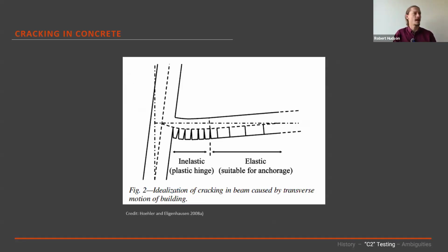The other thing we care about with regards to cracking is the size. The larger it is, the more adverse impact it's going to have on our post-installed anchor connections. Now, there are two numbers to be aware of, and I suspect you're all going to be sick of me saying these numbers by the end of the webinar: a 0.5 mm crack width and a 0.8 mm crack width. The 0.5 mm crack width is very roughly intended to represent service conditions and moderate seismic events, and this is the crack width that a C1 capacity allows for. And then we have the slightly larger one, a 0.8 mm crack width, and this is what a C2 capacity allows for.